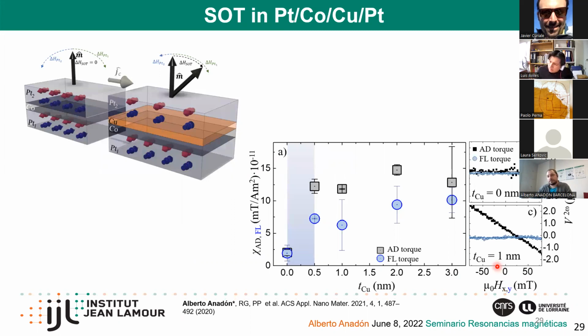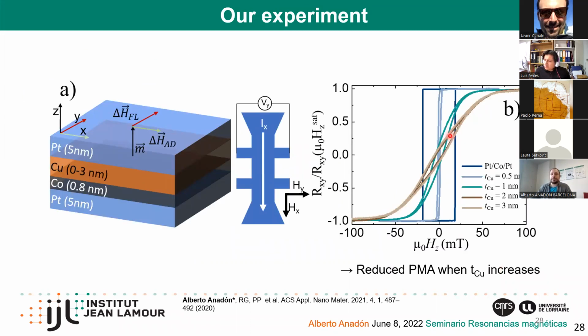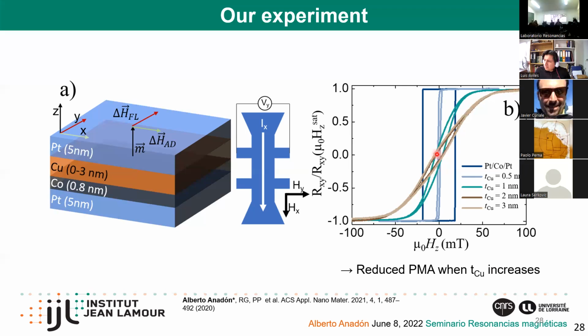Okay, so this is not an in plane system. You can see it's also not completely out of plane and square. If you look at the in plane hysteresis loop, we call this weak PMA because it's not a real full PMA square loop, but it's also not in plane. What we do to measure spin orbit torque here is apply a field, because we are able to apply field in two different directions. So we apply a small field and go into the saturation state, and then we measure the first and second harmonic. That's how I do these measurements.